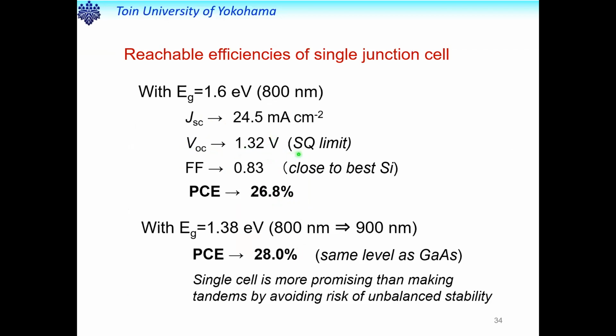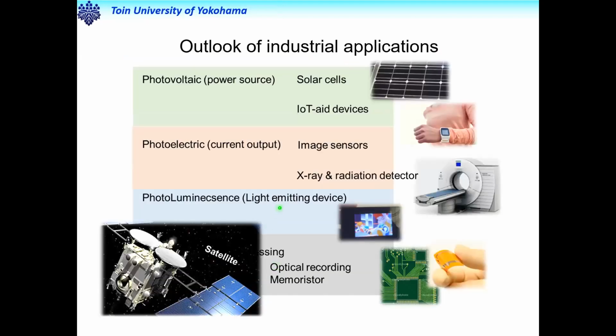The Shockley-Queisser limit is 1.32. If we could achieve this level, the perovskite solar cell efficiency can evolve up to 27%. And also in the future, my dream is to mimic the level of gallium arsenide, 28%. The outlook of application is huge. It's not limited to solar cells, but also image sensors, X-ray detectors, visible light detectors, and light emitting diodes.